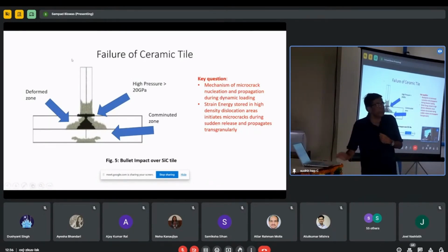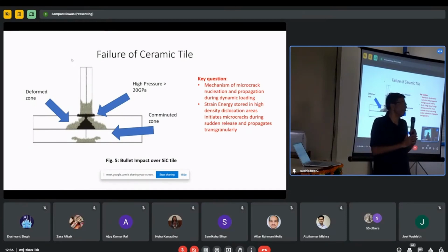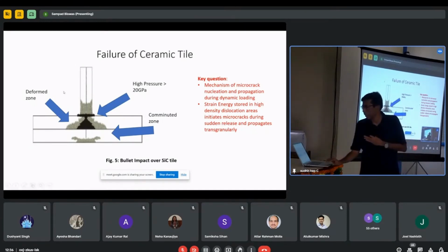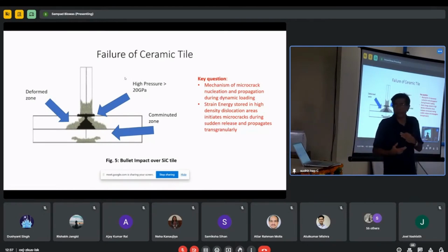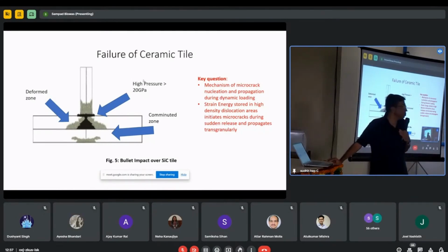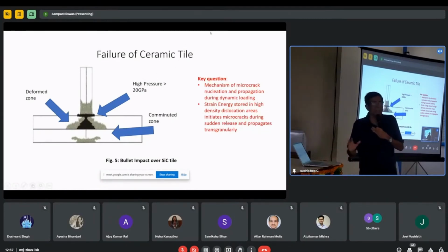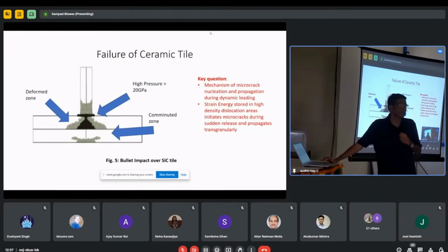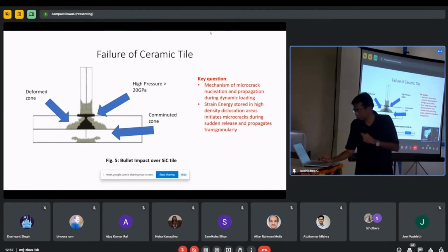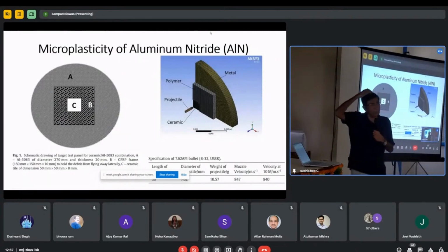Shock waves are generated within the ceramic as well as within the projectile. The sign of the shock waves is different in the ceramic and in the projectile. It depends upon the impedances of the two materials. Impedance means density and the velocity of sound waves within the materials. So this is the way the ceramic fails. Now, in the case of ceramics, aluminum nitride and silicon carbide are the main ones. These are the two main advanced ceramics, which are occupying the top position among ceramic armor materials. Now we have carried out a little bit of work on aluminum nitride.